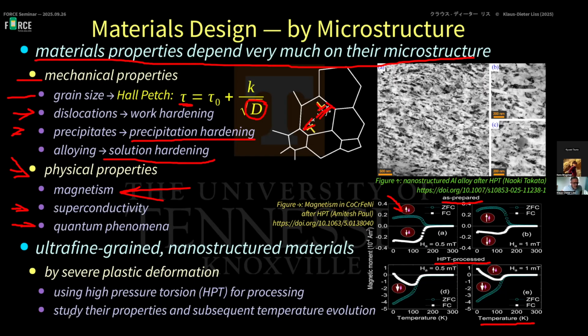Yeah, I like to talk about ultra-fine-grained nanostructured material. So when we make the material really nanoscale and nanostructured. You see here, this is 500 nanometer, and this is a HPT processed sample. This is 200 nanometer here. You see a lot of features in the grains and in the subgrains. So some grains were smaller than 100 nanometer, and the features therein are even 1 order of magnitude smaller. So we're talking tens of nanometers.